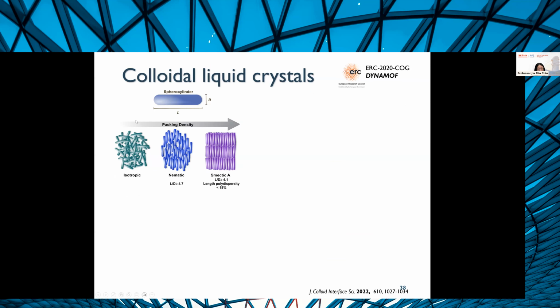So in liquid crystal assembly, the prevailing theories are that you have an isotropic system, and if you have particles of sufficiently high aspect ratio, L/D, represented by the length versus the diameter, it has to have an aspect ratio of at least 4.7 for it to favor packing into nematic phases with this directional preference. If you have a very monodisperse sample, low polydispersity, then you can also create layered order to create these smectic type phases. In this case, you don't need as high an aspect ratio, but it's still pretty high.